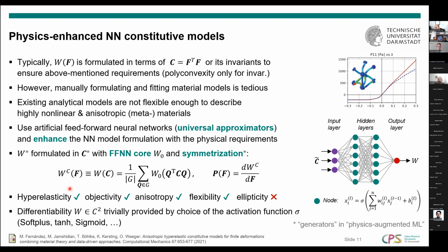So now we have a hyperelastic model that is objective, anisotropic, and has a high flexibility because of this neural network that is used here, which takes the 6 components of C as an input and gives us as an output the scalar strain energy value. It fulfills most of the requirements that you saw on the previous slide, but not the ellipticity requirement that we had. And we need this function W to be twice continuously differentiable.